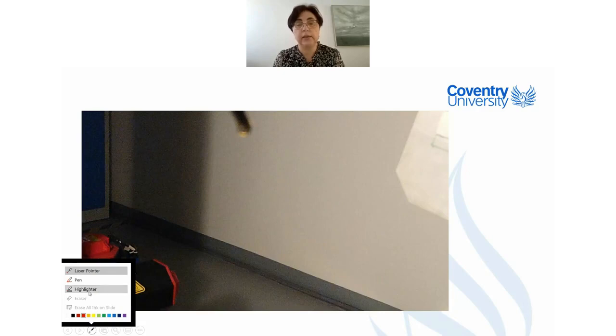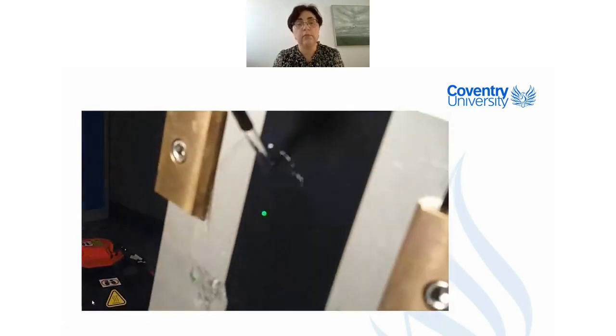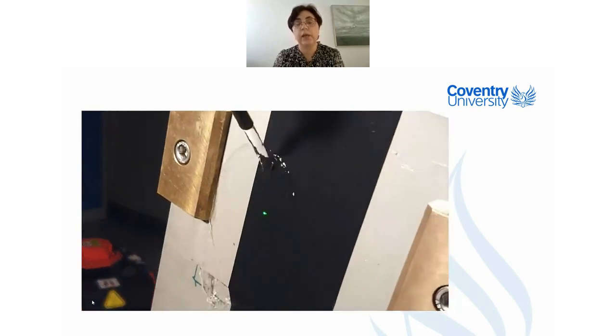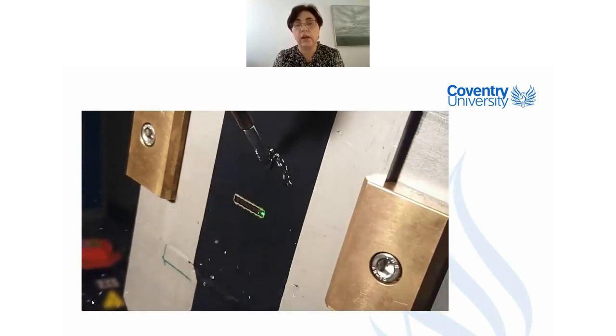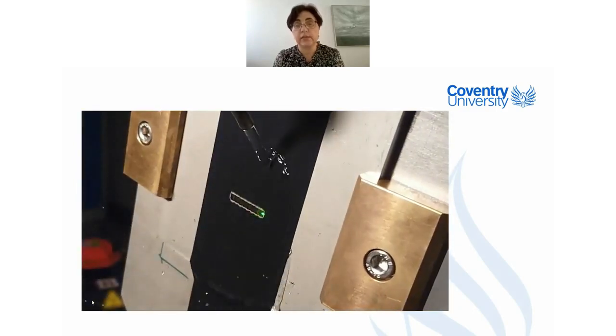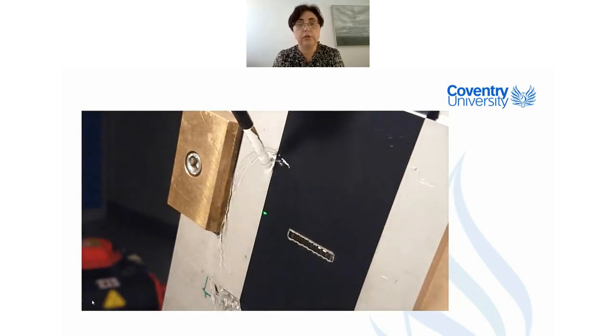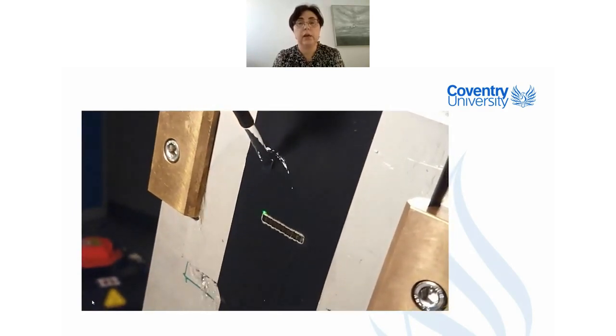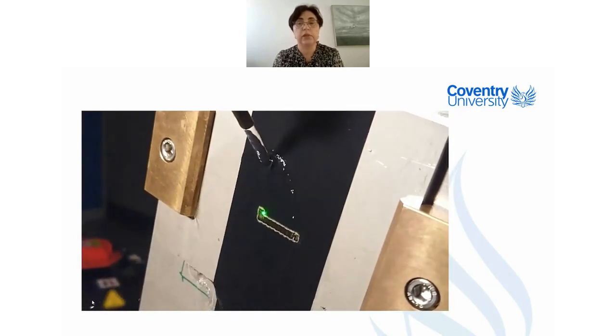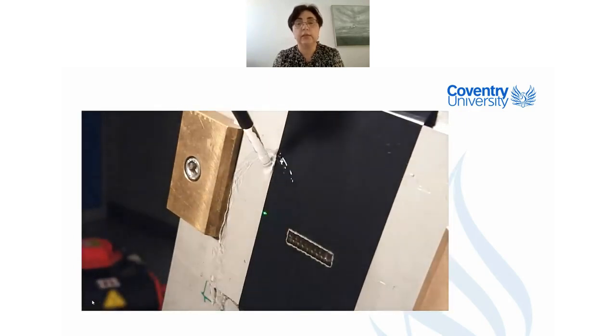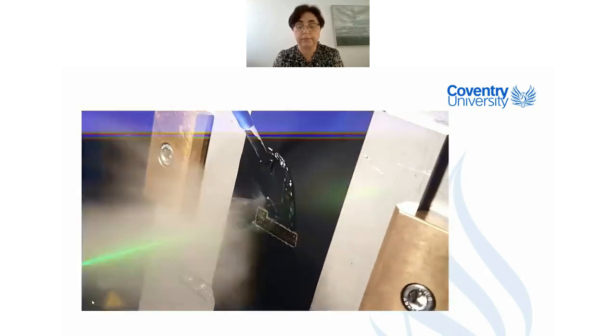In this regime, you're using a laser beam, usually infrared, in the joule energy regime and nanosecond pulse duration. Once this pulse ablates the sacrificial layer, the plasma will be formed, and if there is no what we call confinement media, in this case water, this plasma will expand, leaving very shallow residual stress in the surface. But if we put water on the top, there will be no space for the plasma to expand. A shock wave will be created and propagate inside of the material.